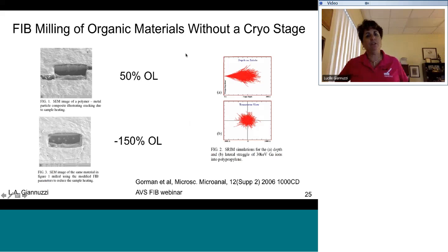People always ask, how do I FIB mill organic materials and polymers? And you can do this, in fact, with a cryostage or without a cryostage. Now, without a cryostage, you have to consider what material you're FIB milling and what is the width of the collision cascade. In this case, the collision cascade for polymers is generally going to be much wider because these bonds tend to be a lot weaker than in